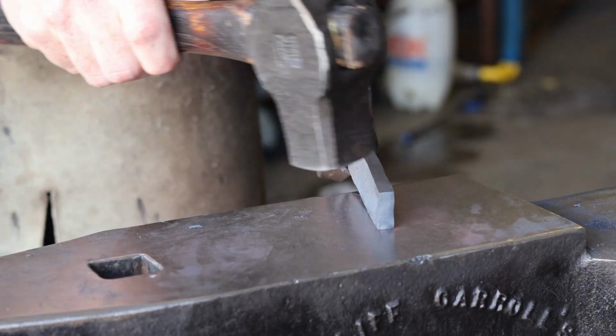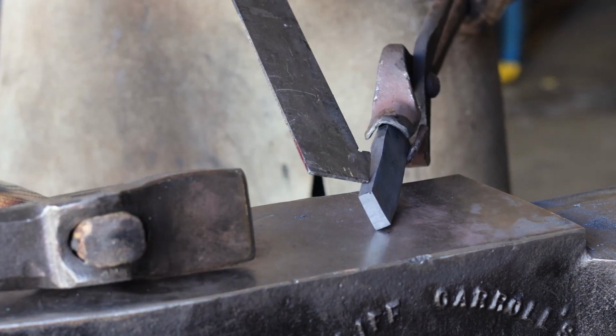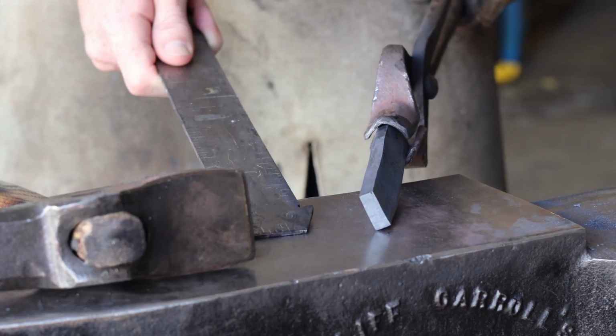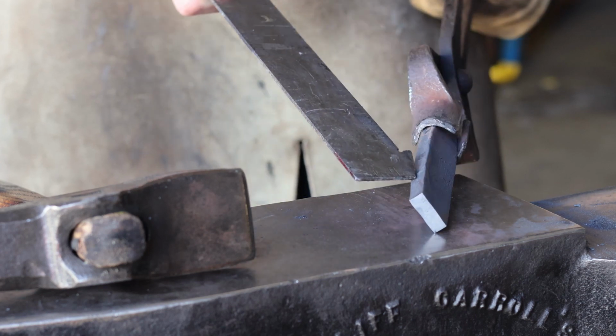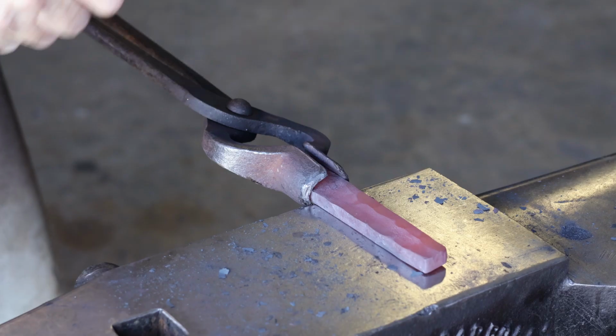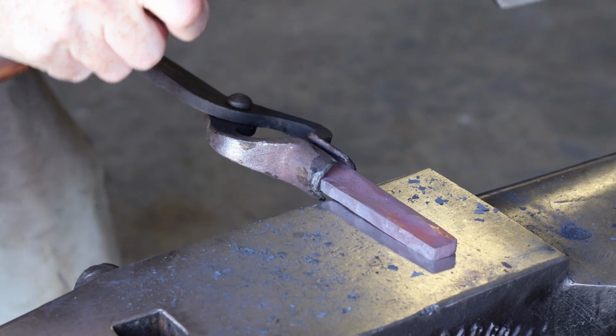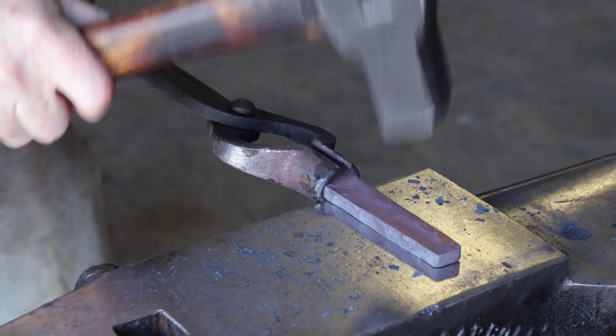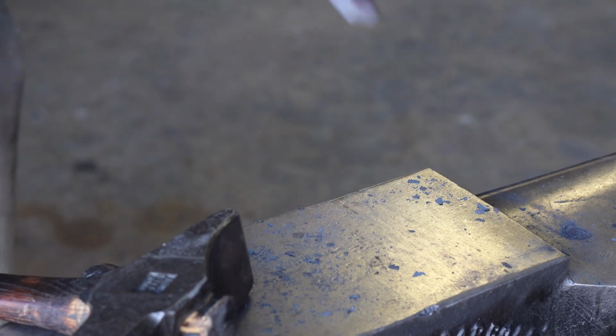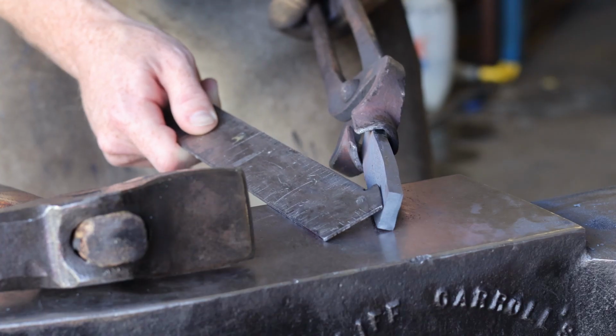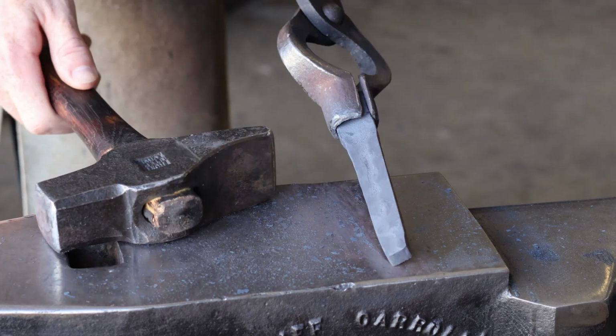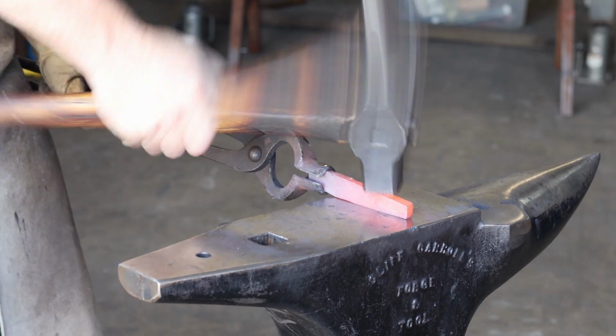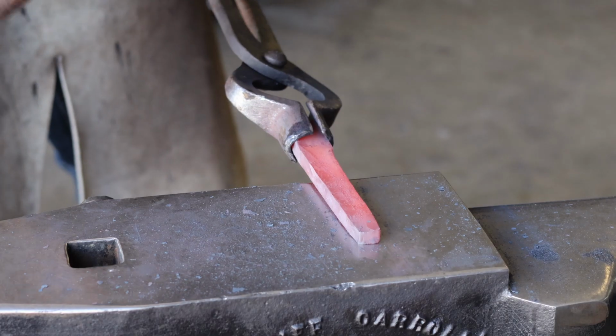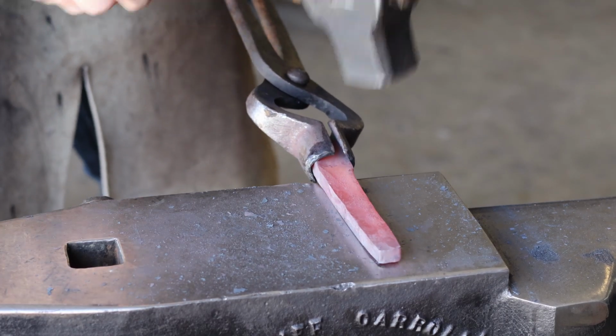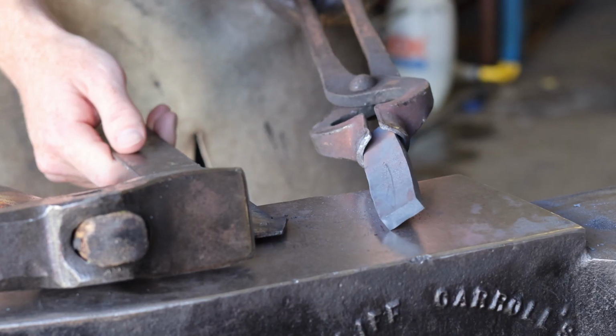And the answer to that question is no, because as you forge on the edge of a piece of steel, the blow itself is more heavily concentrated on the edge that you're forging, and the rebound off the anvil is more heavily concentrated on the opposite edge, which means you're going to get more steel moving in the first few layers of atoms of the steel than you do in the middle. Because of that, you see a lot of spreading of the steel near the point of the blow, and not so much in the center. So you end up with kind of mushrooming of the steel over the center, and if you forge that down to where the two mushroomed edges meet, you'll develop a cold shut and a big crack that runs right down the center of your piece.